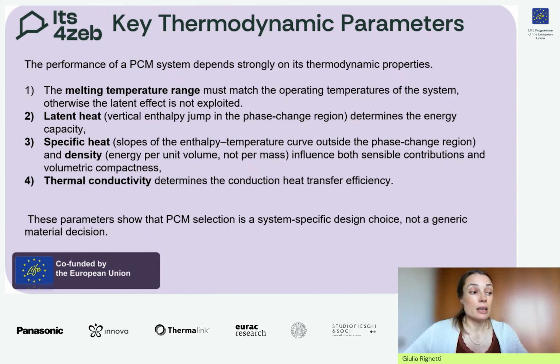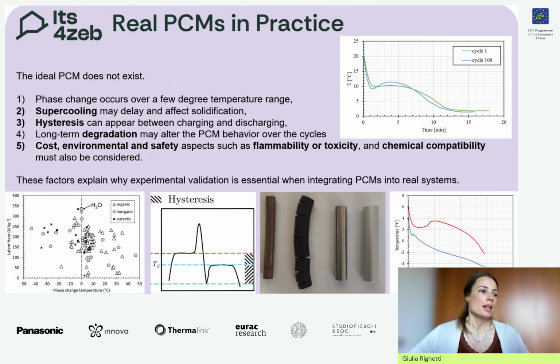Finally, we have the thermal conductivity, which determines how fast the energy can be charged and discharged. This is often the bottleneck of latent storages, which have to be enhanced with particular metal geometries and structures. So altogether, these parameters show that the selection of the PCM is not an easy decision. It's not just a generic material decision. It has to be integrated in the whole system design. Then it's important to be realistic.